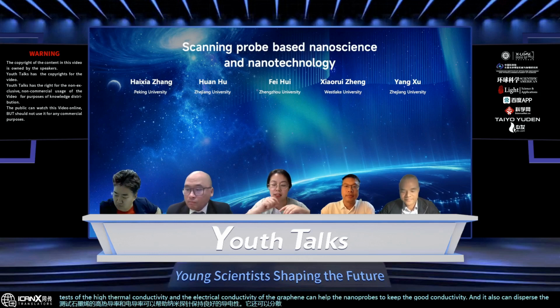Because of the high electrical conductivity of the graphene, that can help the nanoprobes keep good conductivity, and it also can disperse the heat caused at the small contact area. It will help to disperse the heat at this tiny contact area. So in that case, it allows us to make this graphene coated tip live a longer time. So this is the big advantage of this.